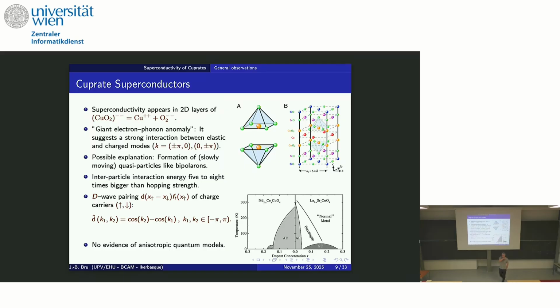And the pseudo-gap temperature means that if you analyze the excitation spectrum of your system, of your pairs inside your model, you realize that there is a gap for certain, particular quasi-momenta. In particular, for this kind of momenta, 0 pi. This is where the gap appears, and it appears at very large temperatures as compared to the superconducting temperature.